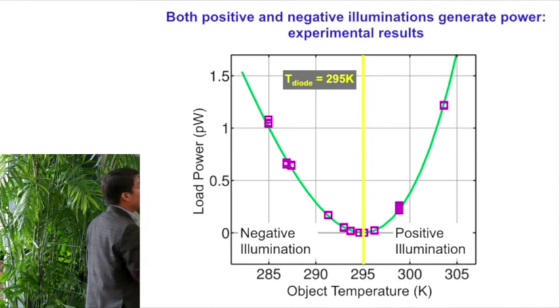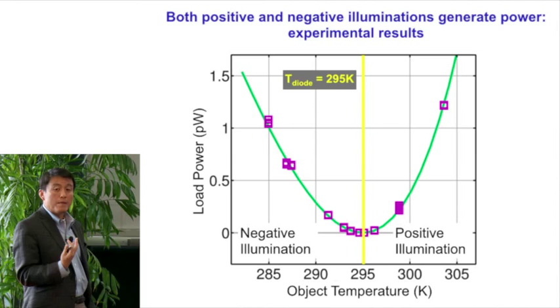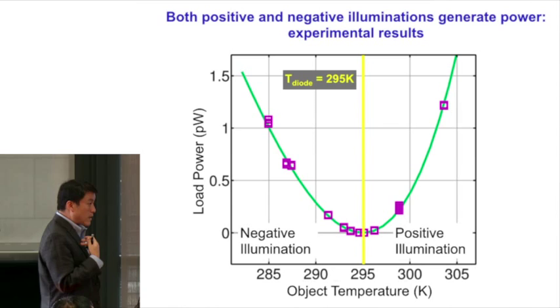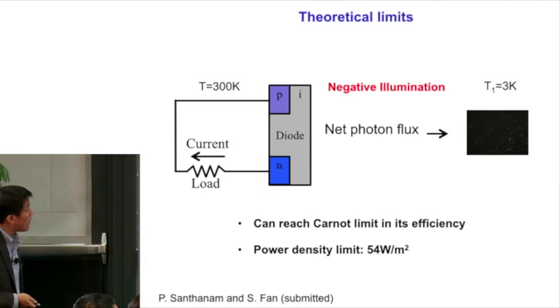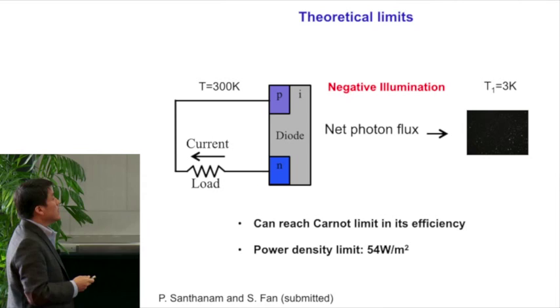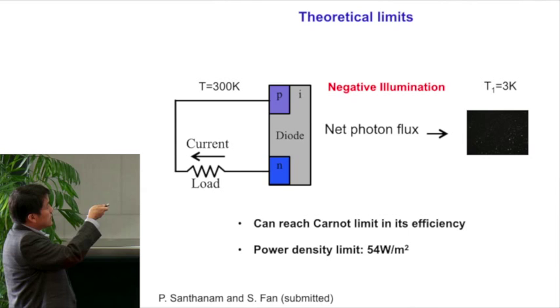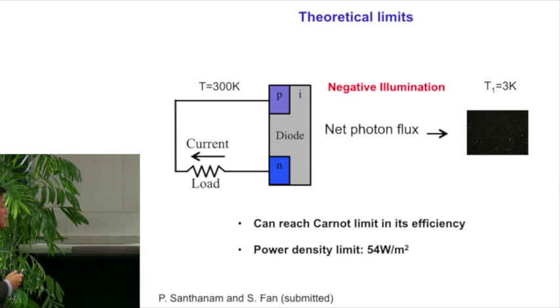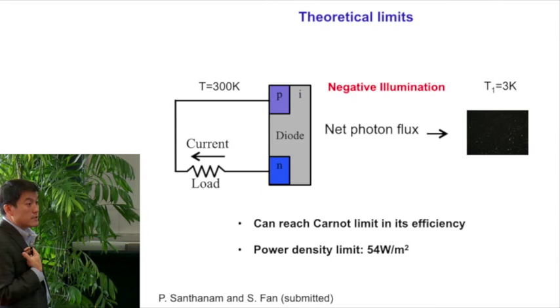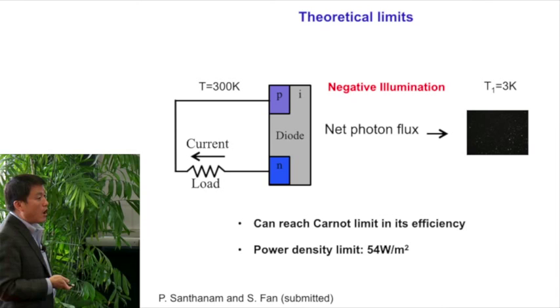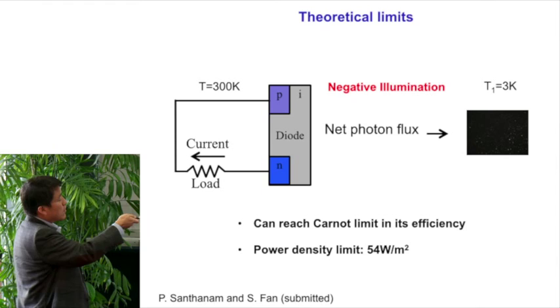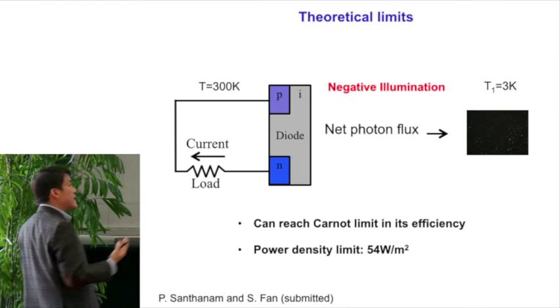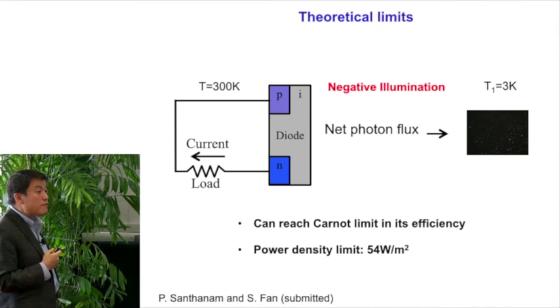But on the other hand, given an idea like that, one can ask, what exactly is the limit of the efficiency as well as the power density that you can get out of this kind of scheme? So we did a theoretical analysis assuming a perfect diode without radiative recombination facing a 3 Kelvin background when the diode itself is sitting at 300 Kelvin. And the theory actually reveals two things. One of them is that with proper design, this kind of setup can actually reach the Carnot limit in its efficiency. And therefore, it's actually a theoretically ideal scheme of benefiting from the thermal radiation from, for example, the Earth to a very cold background. The second point is that the maximum power density in terms of electricity that you can extract turned out to be on the order of 54 watts per meter squared.